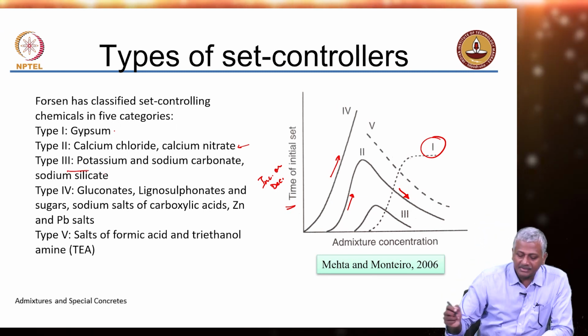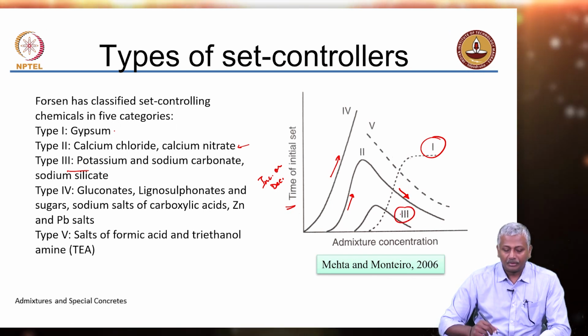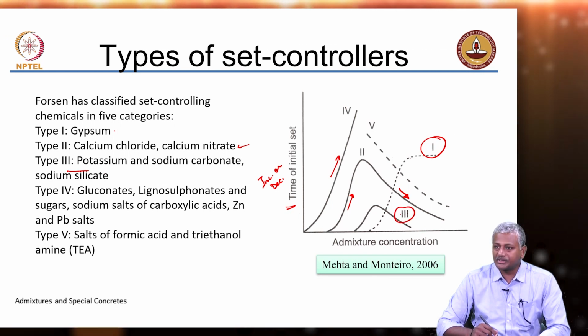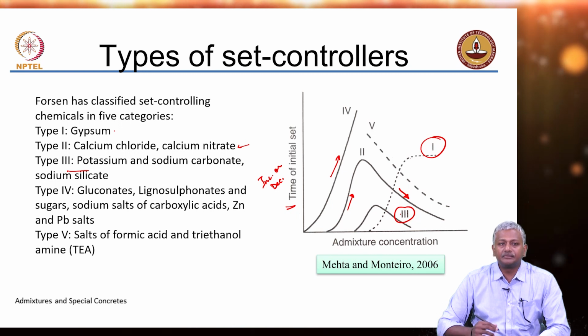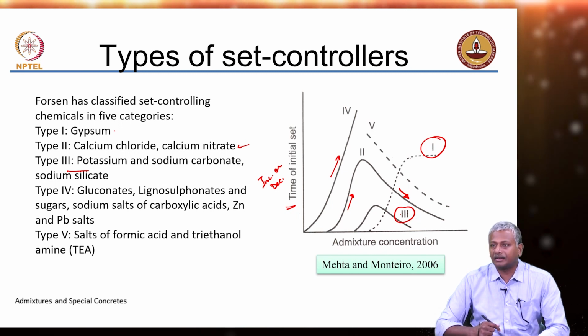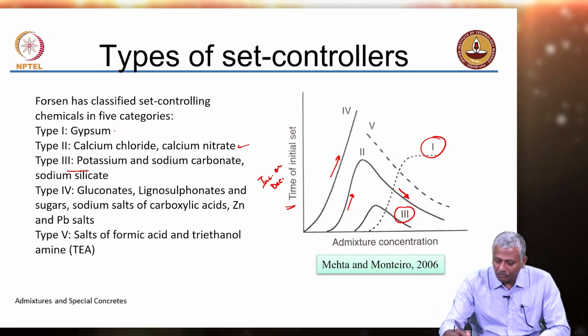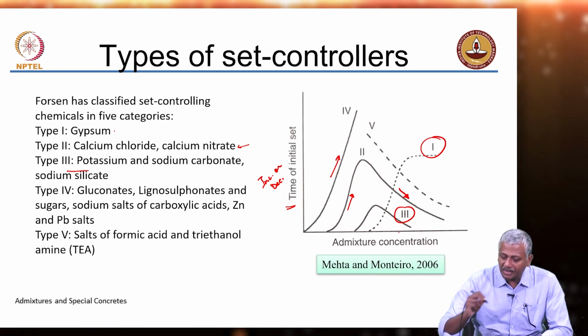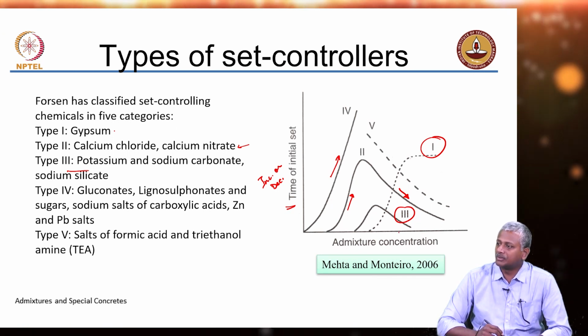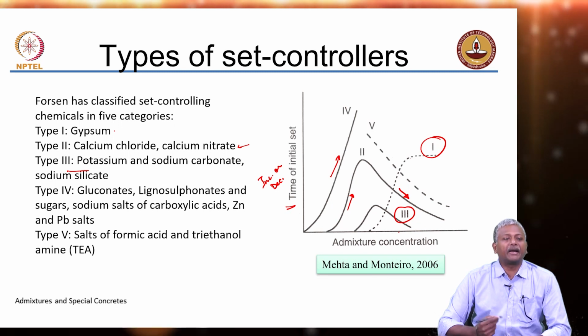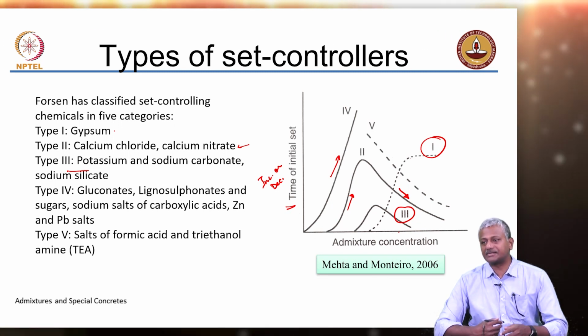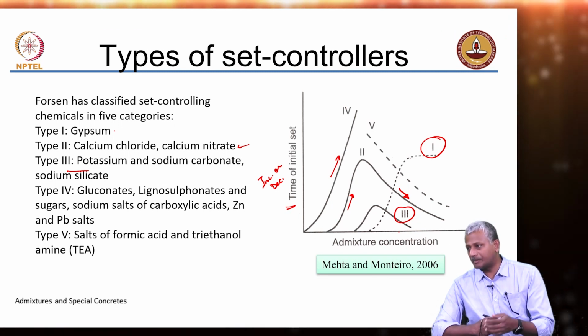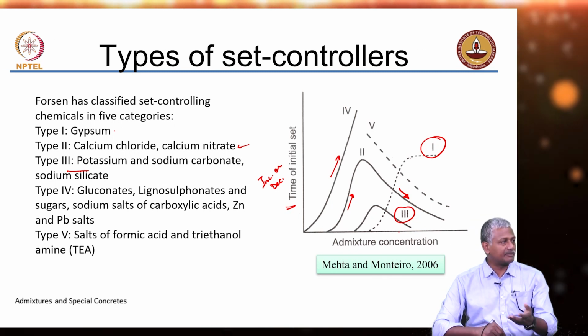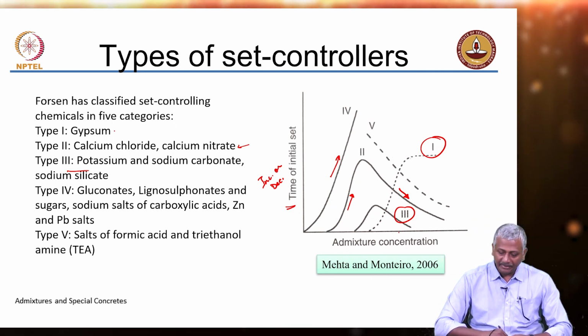Type 3, again, has a similar effect: an increase in set time at low dosages and acceleration of the setting at high dosages. But what is the difference between type 2 and type 3? The impact of the admixture is lesser for type 3 as compared to type 2. Type 2 has the maximum impact, type 3 has less impact.